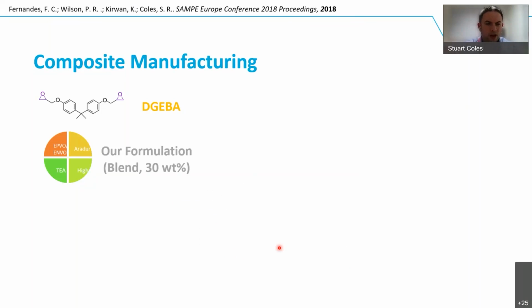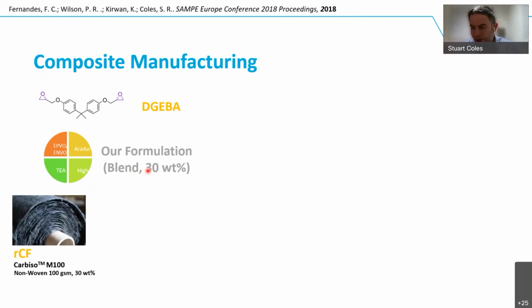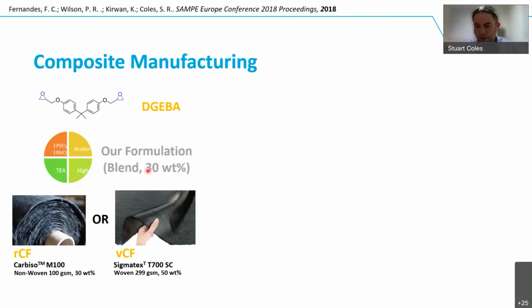So again, we took our formulation. This time it was a 30 weight% blend rather than the 10 or the 50, just to try and get a nice optimized system. We followed through our systems again, but this time we looked at it with recycled and virgin carbon fibers just to see how well we could push this. If we had the best type of reinforcement that we could think of, were we really going to start to absorb some of the impact, and would we notice a difference between the DGEBA system and our resins?